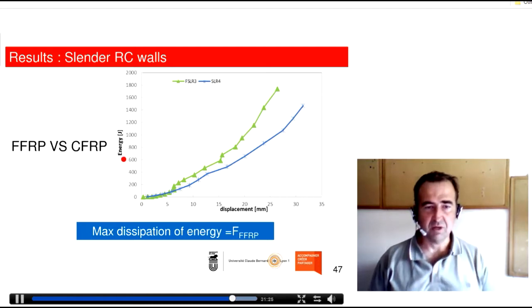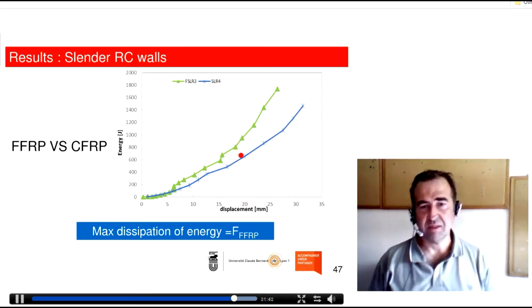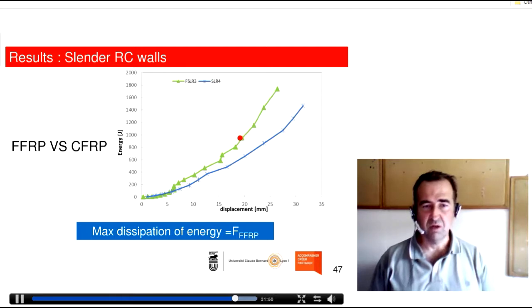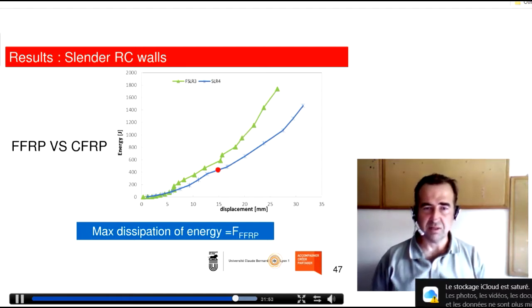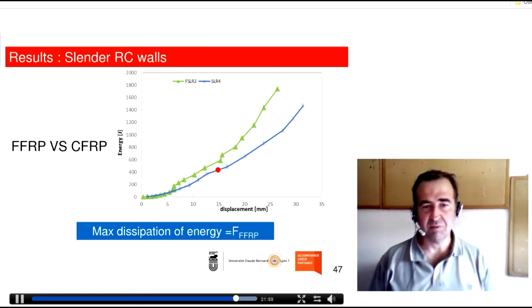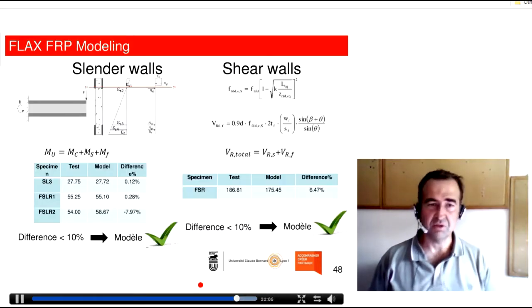If we calculate the energy dissipation as a function of displacement, you have here the slender wall strengthened with carbon fibers, and here the total energy dissipation and the elastic one. For the same level of displacement, which is here, it's very interesting to see that we have a higher energy capacity of the wall, a 10 to 20% increase in the energy capacity of the wall. It means that flax fibers are more suitable than carbon ones for seismic strengthening.